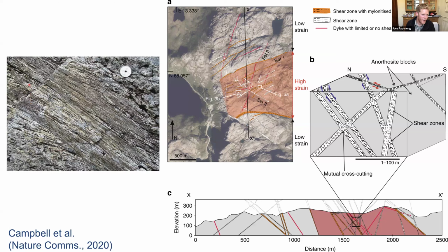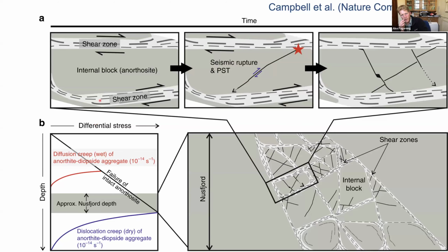So here is a mylonite. The dark material here is interpreted as pseudotachylite. So it's pseudotachylites that have then been mylonitized, and the white is anorthosite, but finer grained in these zones. So just to jump straight to how we interpret this, you have shear zones that deform by viscous flow. We're at temperatures of 700, 800 degrees, so this sort of depth on the schematic diagram.